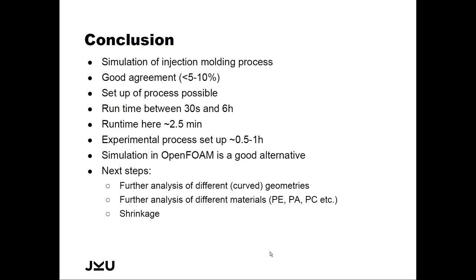With this work we can run simulations of injection molding in OpenFOAM and find a rather good agreement — a deviation of 5 to 10 percent between experiments and simulation. We can run the simulation before the actual mold setup to find safe process parameters, ensuring we do not reach the maximum pressures of the mold or machine, and we can also determine when to switch off the high packing pressures to consume less energy. For this simple plate geometry the simulation ran in just two and a half minutes, while the experimental setup took half an hour to one hour.